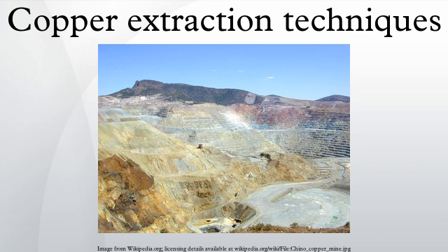To improve the process efficiency, lime is used to raise the pH of the water bath, causing the collector to ionize more and to preferentially bond to chalcopyrite and avoid the pyrite. Iron exists in both primary zone minerals. Copper ores containing chalcopyrite can be concentrated to produce a concentrate with between 20% and 30% copper in concentrate.